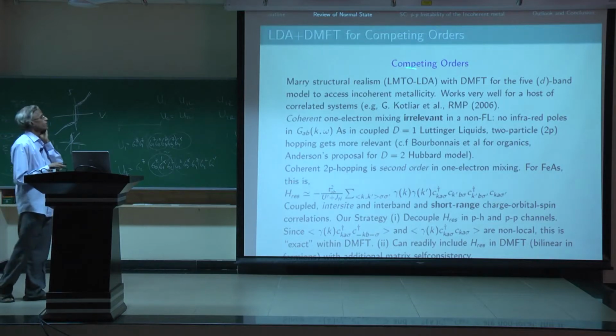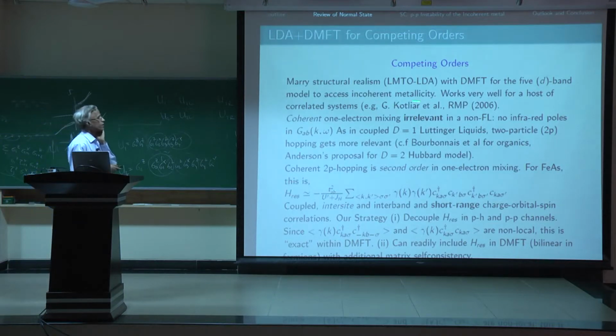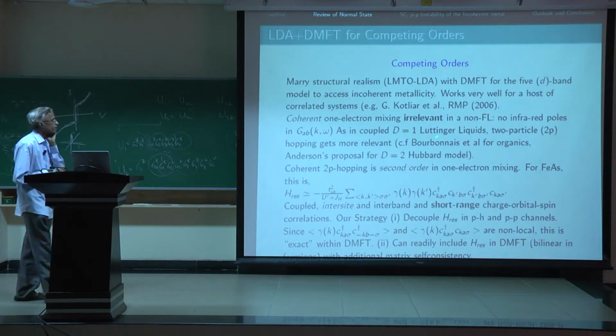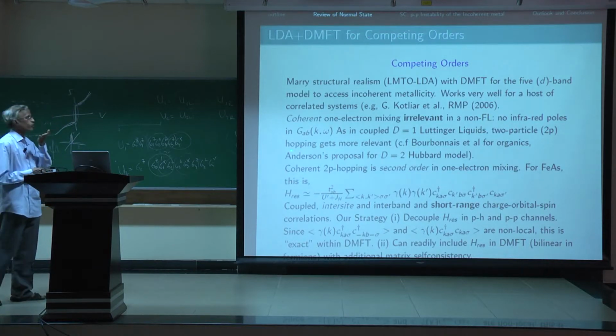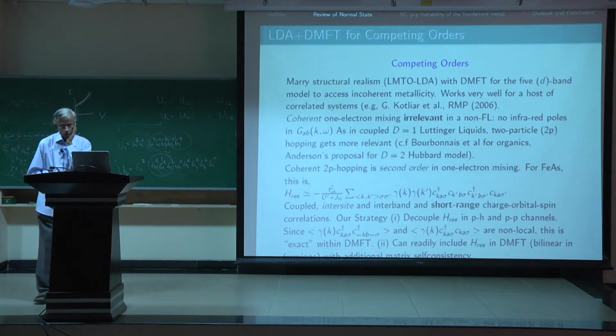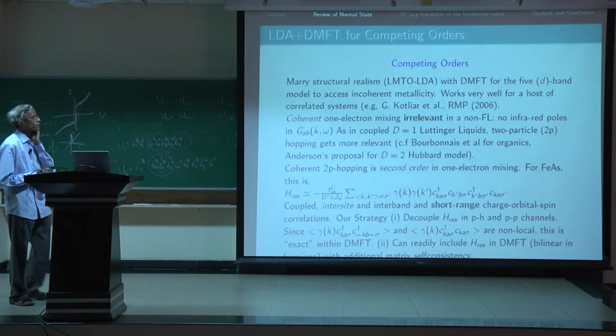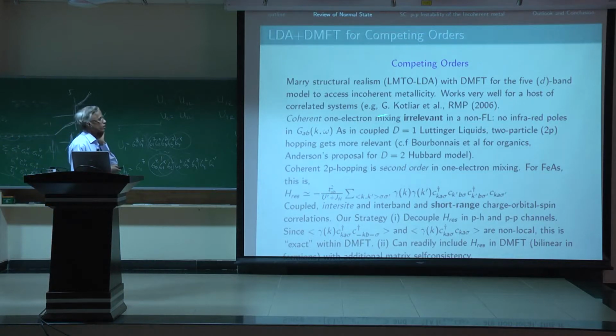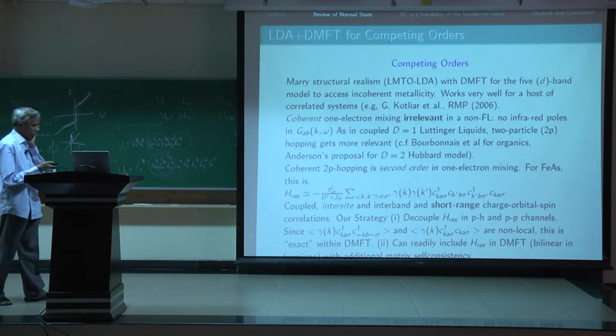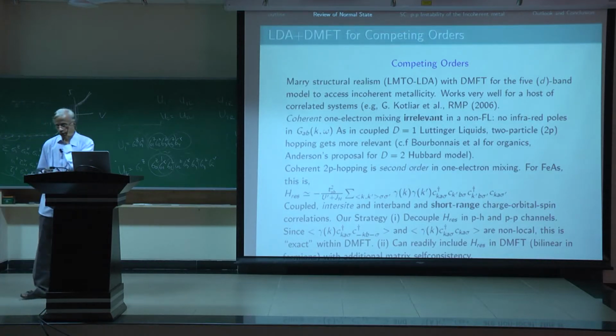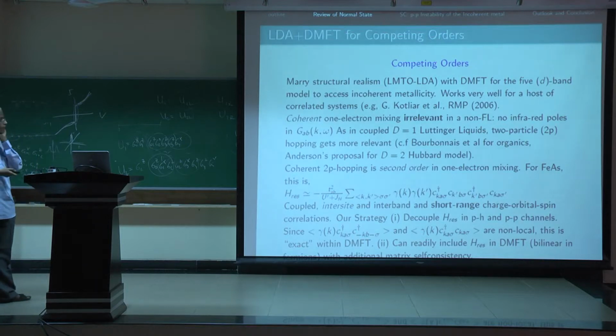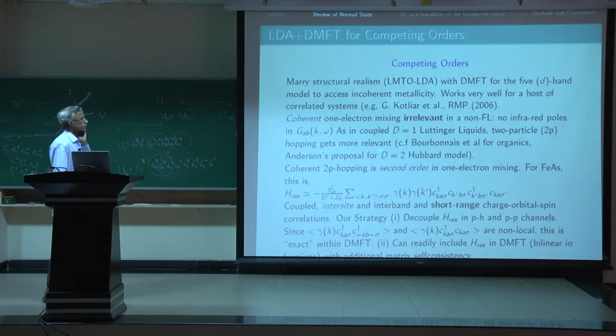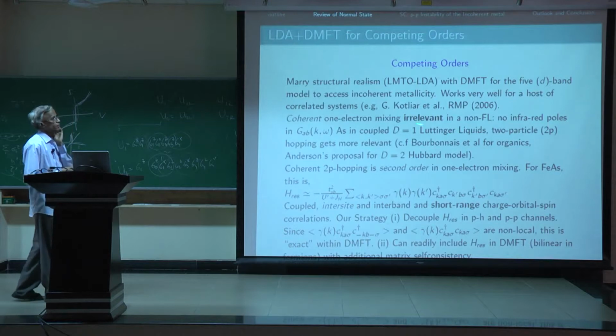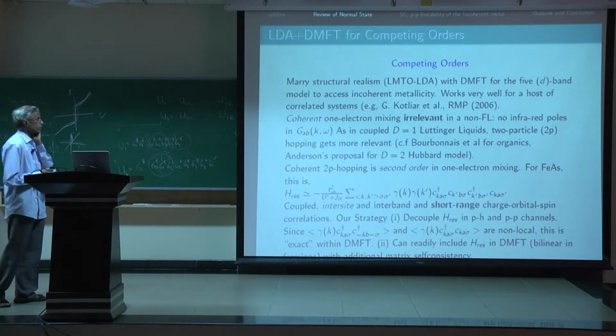Okay, but having an incoherent metal state without Landau quasi-particles immediately suggests that coherent one-electron mixing is going to be an irrelevant process, because if quasi-particles are very short-lived, the hopping from one side to another is not a coherent process. So, in particular, any ideas of nesting of well-defined Fermi surface sheets would run into trouble, because of the very absence of the quasi-particle description.